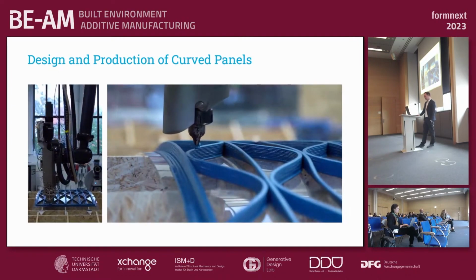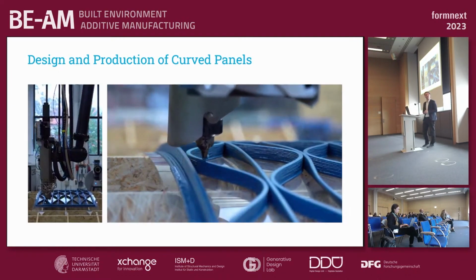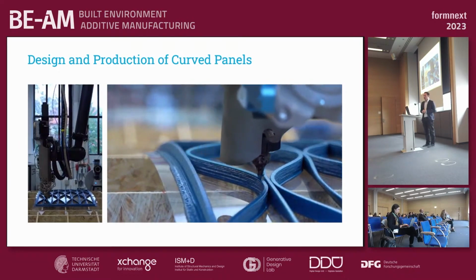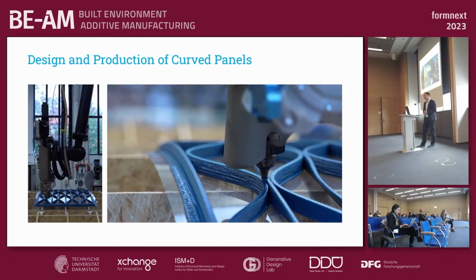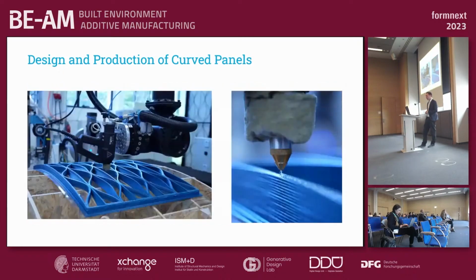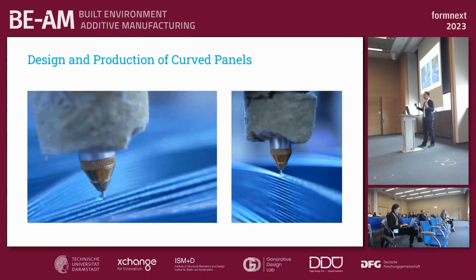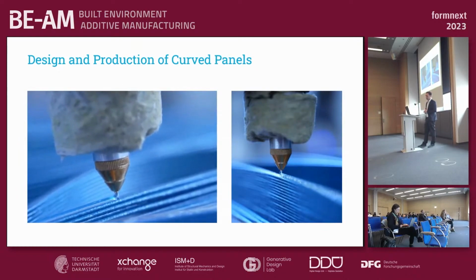You can here see a very thin sheet of glass, only 0.7 millimeters thick. We can heat it from below, and then we can directly print on the curved surface. And we have a curved core structure. The next step is to glue it somehow, and we already heard about the acrylic, which is UV hardening, but it's very like honey, so when you have a curved surface it will flow down to a certain point. So we are investigating new methods to glue it. One promising example could be the hot melt, which we are using here. We just mounted a hot melt glue gun on the left side of our robot, and then we took the same path as the last layer of printing, applying the hot melt.